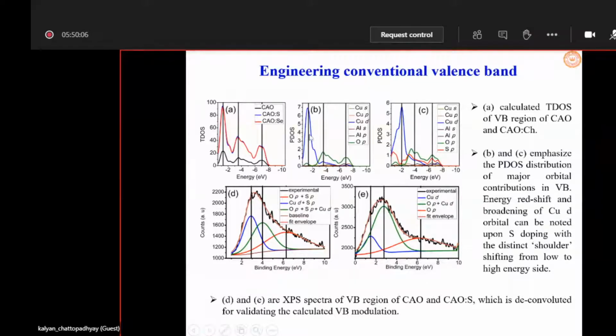density of states contributions. This is for the pristine sample, so you can find copper, aluminum, and oxygen. And this is for the sulfur incorporated, when sulfur is there. So now the lower panel actually represents the X-ray excited valence band spectra. You can see, okay, this is actually for the undoped system, and this one is for the doped system. So you see, just compare one thing.